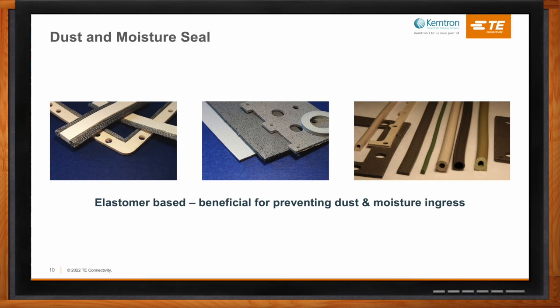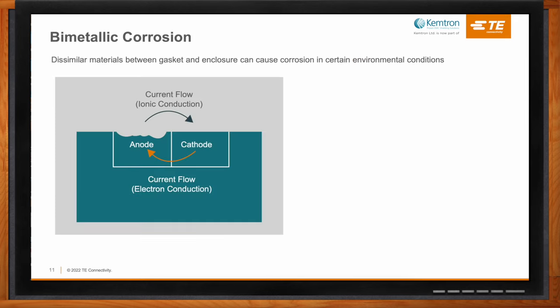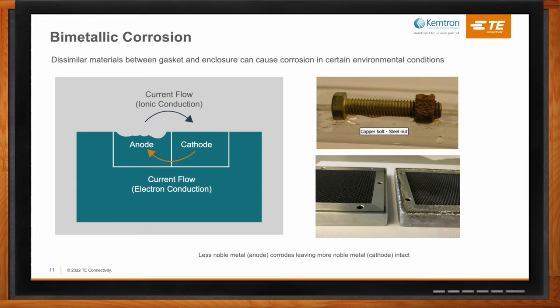What about the materials of the enclosure and the gasket — do they need to be made of the same material? In certain environmental conditions, if you have dissimilar materials in contact with each other, this can cause what's known as galvanic or bimetallic corrosion. This corrosion will increase the surface resistance, which will reduce the shielding performance. If the application is in an environment where galvanic corrosion is a concern, it's important to match as closely as possible on the galvanic scale the EMI gasket material and the mating surface material. This is why many of our EMI gasket materials are offered with different material options.